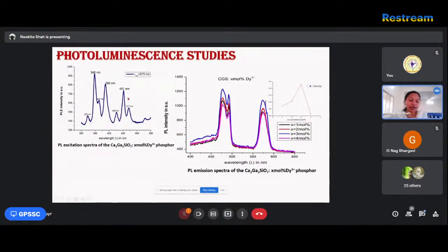This is the excitation spectrum of the calcium gallium silicate phosphor doped with dysprosium ion. The prepared material shows several excitation peaks at 348 nanometer, 386 nanometer, and 451 nanometer, in which the 348 nanometer wavelength is used for monitoring the PL emission spectra of the dysprosium doped calcium gallium silicate phosphor. And this is the emission spectrum of the dysprosium doped calcium gallium silicate based phosphor.